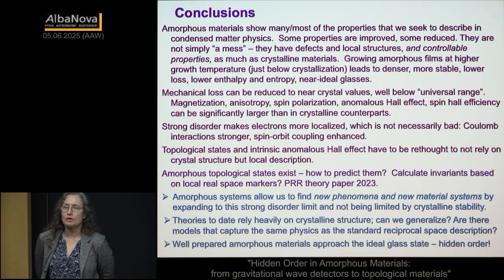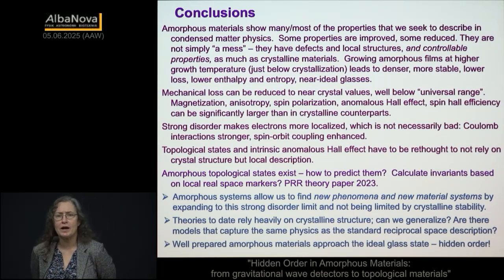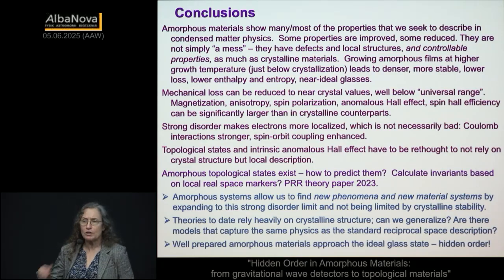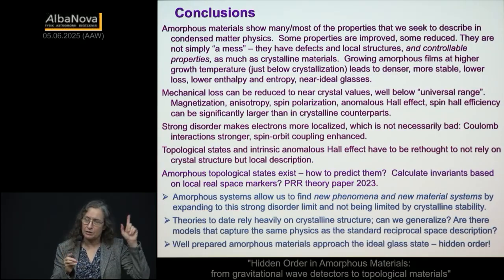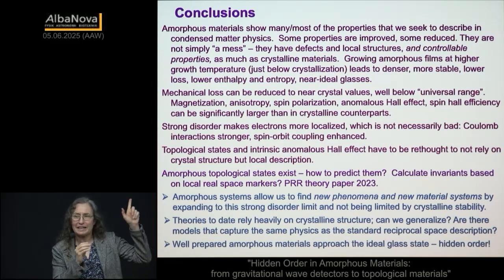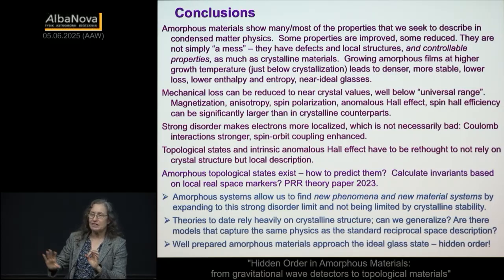You do. So did people understand the question? There's literature going way back on this diffusion limited aggregation. If you grow at low temperatures, you very much get that. In fact, I don't know if you noticed in the amorphous silicon I showed, which was grown by E-beam evaporation, you could actually see these columns in there. And that's a common thing in E-beam growth.